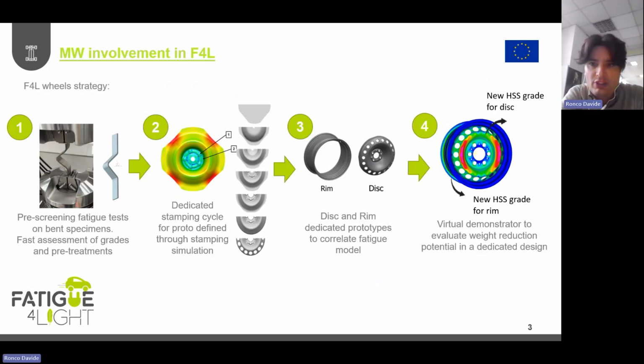What was the MW strategy for this European project? At the beginning, we made a pre-screening fatigue test in order to evaluate which material can be suitable for our needs. And when we defined the correct material, we studied dedicated stamping cycles and a dedicated stamping sequence to produce the parts with this new material grade. We prepared the samples and the prototypes, and we correlated the fatigue model. And then at the end, we created a virtual demonstrator with all the concepts and characteristics we studied during the Fatigue4Light project that include this innovation, with the scope to reduce the wheel weight by 15%.